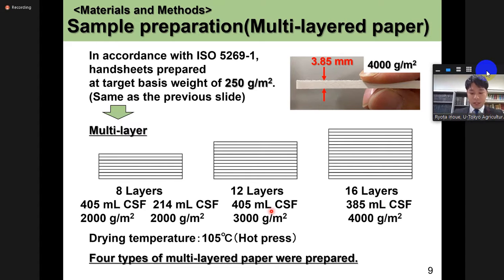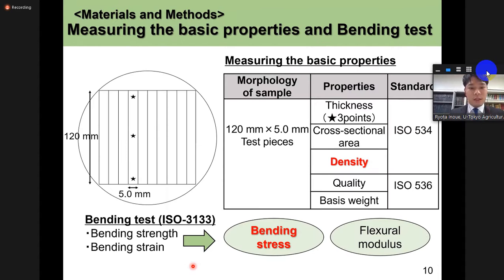We dried the multi-layered paper by using a hot press at 105 degrees. We obtained 4 types of multi-layered paper. Now let me explain about measuring the basic properties and the bending test. We cut the multi-layered paper into 120 millimeters by 5 millimeters test pieces.